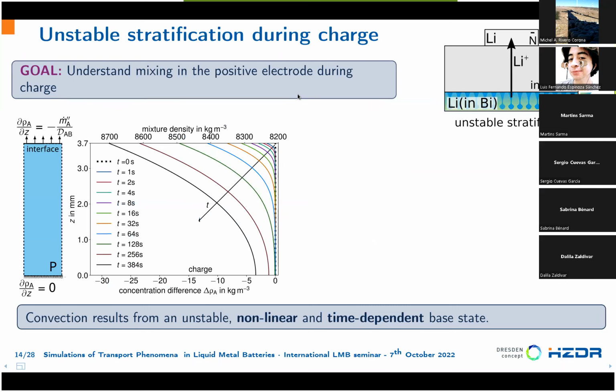First, it's important to discuss a bit how solutal convection works. So we are removing the light component from the top of the positive electrode, and this generates these profiles. These profiles are still in pure diffusion, as the ones that we saw for the discharge. And here we see that on top we have a heavier fluid, so the density on the top is larger than in the bulk. And this results at some point in convection.